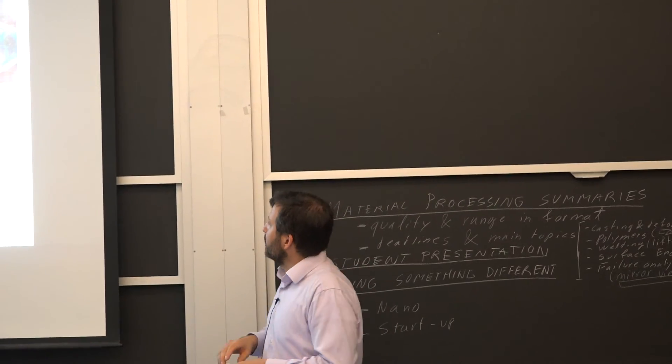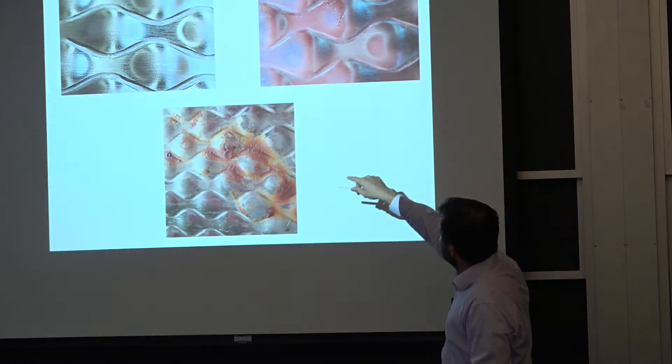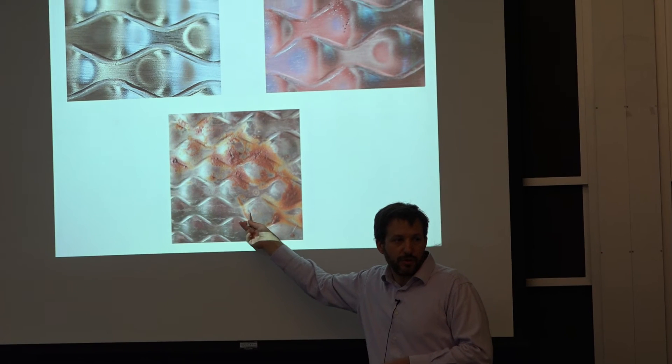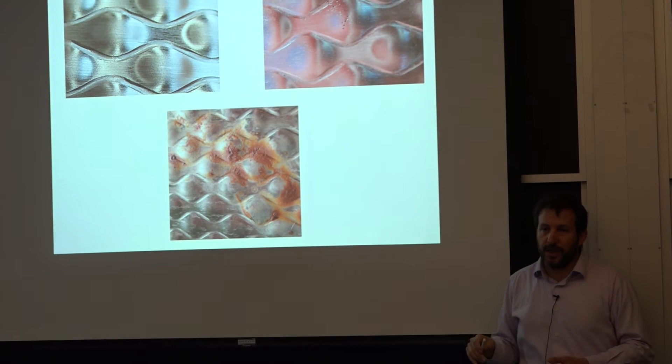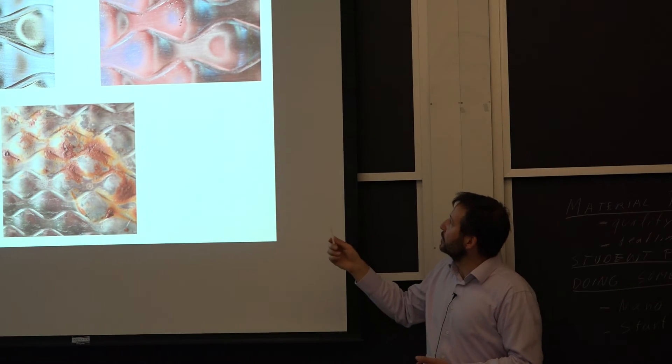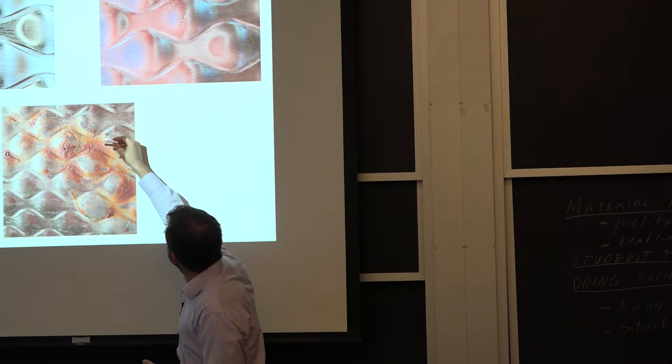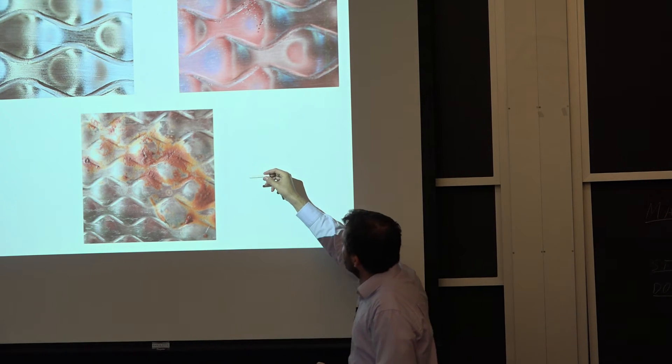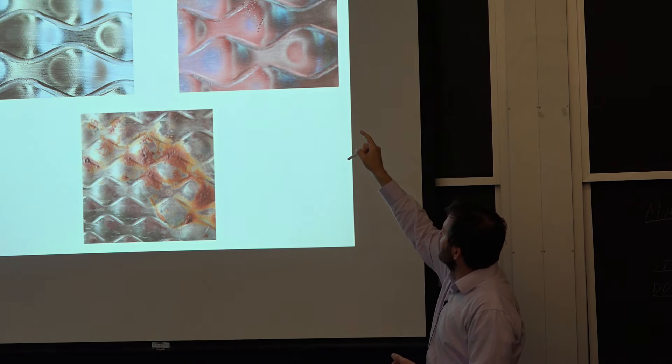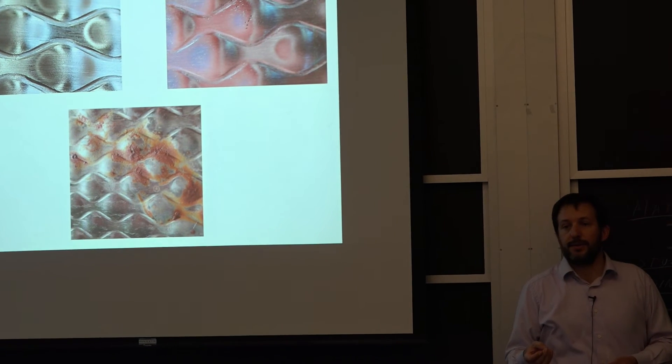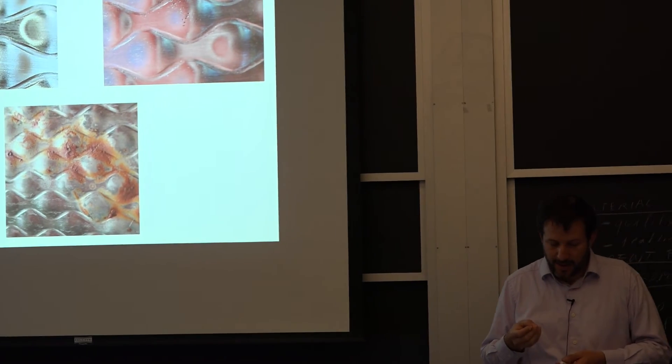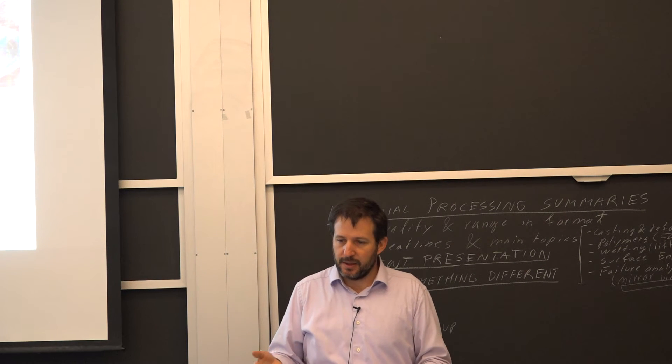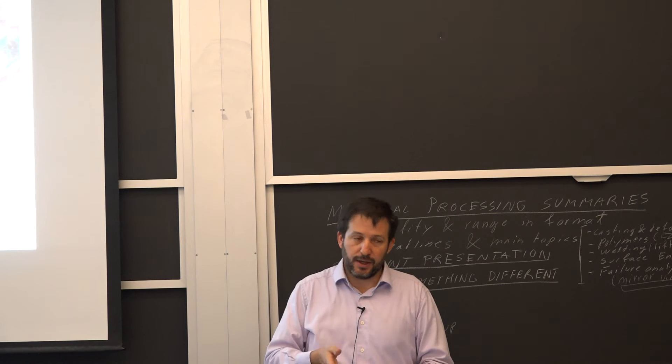This example is for architectural purposes, the Miami International Airport had a lot of these embossed brush stainless. They had this process of working on the pavement. They did essentially an acid etch to prepare the surface, put a coating and they didn't have enough ventilation so the entire room kind of got pretty acidic just the moisture in this case. So it started to pit the stainless. This is how it looks after a replacement or partial replacement. Very similar to what we've seen in the copper, pits go very deep at one specific site. The only way not having to replace all these panels was to just put a little coating to protect against the chlorides.